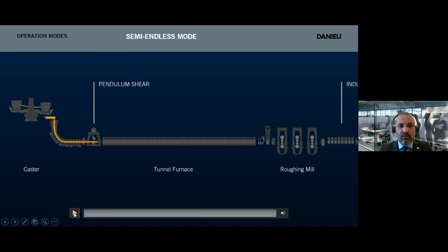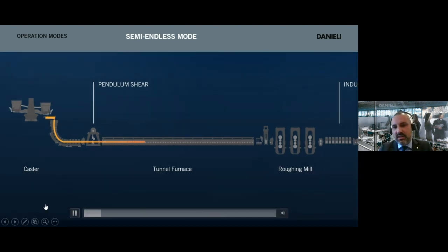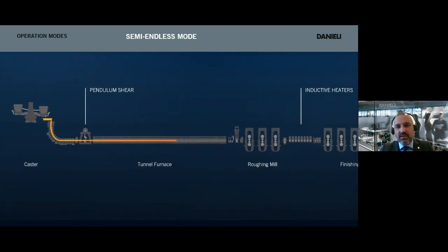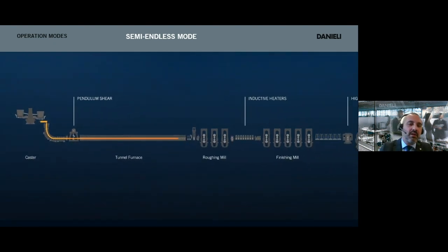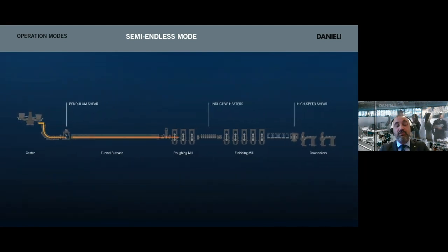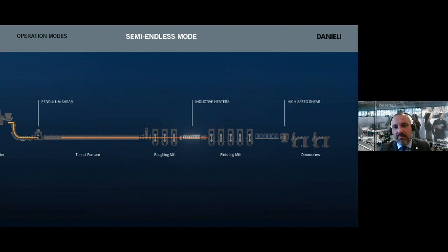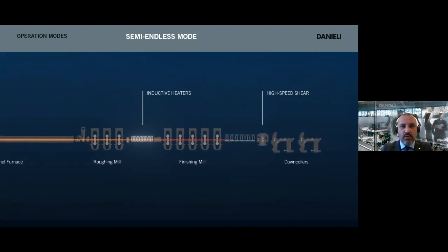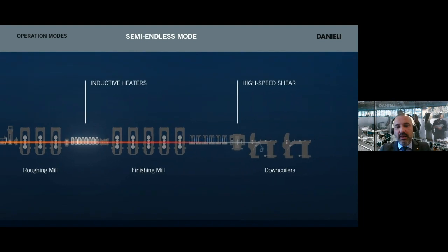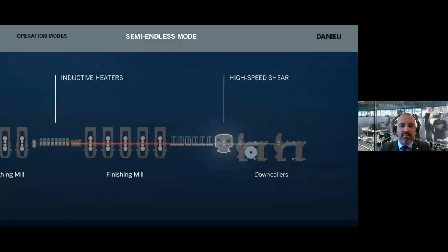The second rolling mode is the semi-endless. Semi-endless consists of making a longer slab, on which the length is based on the furnace length itself, and this mother slab is rolled into one piece, could be with or without application of induction heater, through the rolling mill, and the coils are cut into length by the high-speed shear at the down coiler entry side. By applying semi-endless, of course, we can also apply flying gauge change in order to reach thinner products than what you can get in coil-to-coil mode.